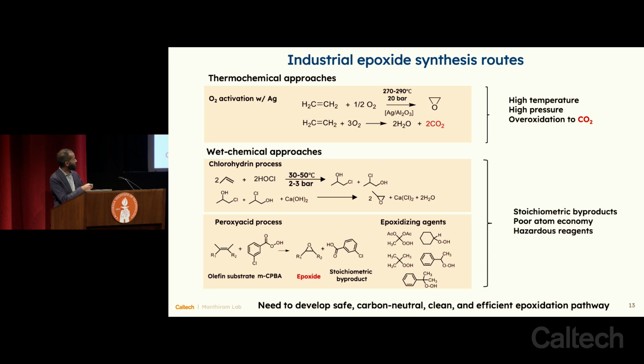One could instead use peroxides. These are relatively popular processes now, starting with an olefin, reacting, for instance, with a peroxide like metachloroperbenzoic acid or hydrogen peroxide. You can make the epoxide as a product, but my friends who are process chemists tell me that these reactions remain relatively dangerous at scale. There continues to be, on average, 1 fatality a year from epoxidation plants. And these are reactions that all too often go wrong because you have organics in contact with really strong and reactive oxidizers. So we can see here that there are a lot of reasons to innovate on epoxidation chemistry: the carbon footprint, the presence of environmental discharges that are unfavorable, and safety, all of which conspire to motivate us to make new methods of driving epoxidation.